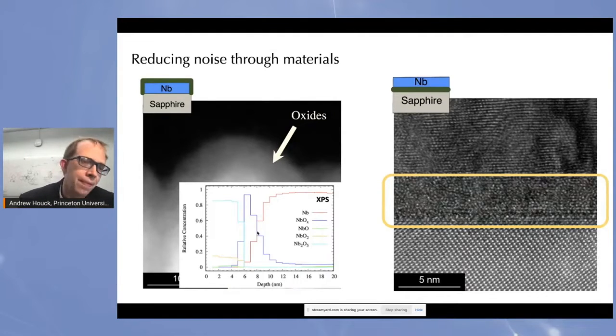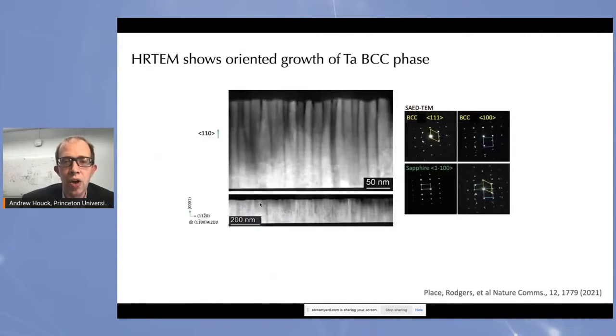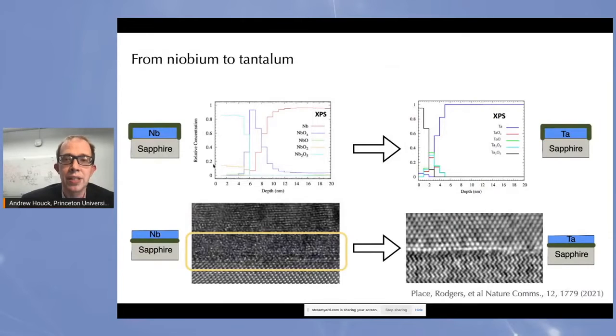So working with Bob Cava and Natalie De Leon, we started thinking about other materials we could use in place of niobium and how we could develop a full process to build the kinds of quantum systems people need out of new material platforms. We settled on a tantalum approach. It turns out that growing tantalum films is difficult in the proper crystal structure, but we came up with a process that allows us to grow the right crystal form of tantalum. And you can start to look at these kinds of things that we were looking at before for these new tantalum films. So unlike the niobium films that are dominant throughout industry, you can see that the oxide layer becomes incredibly thin, which is quite likely to be good.